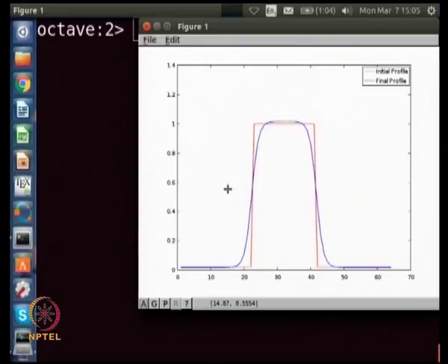Okay. So, now the code is evolving. The point behind this code is also to show that even though the Cahn-Hilliard equation is meant for doing spinodal decomposition, if you are outside of the spinodal regime, which is like the growth regime, then the same equation should also describe growth, because we said that the Cahn-Hilliard equation is just a generalized diffusion equation. So, in the special case where there is no negative diffusivity, it should reduce to the usual diffusion equation. Okay. So, that is what we are seeing, and as you can see, the composition profile changes.